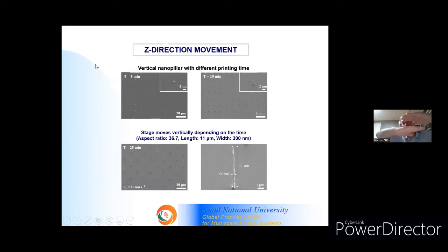We can move this substrate in the Z direction, lowering the substrate. Initially at 5 minutes it starts, at 10 minutes it grows, at 25 minutes, a very high aspect ratio nanowire shape forms since we move the substrate. This aspect ratio is 36, diameter 300 nanometers. We used a 4 micrometer hole, so this electrostatic lens generates a 300 nanometer diameter wire, very long, high aspect ratio wire.